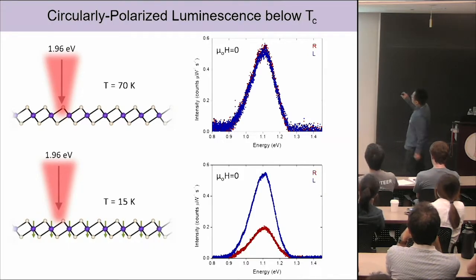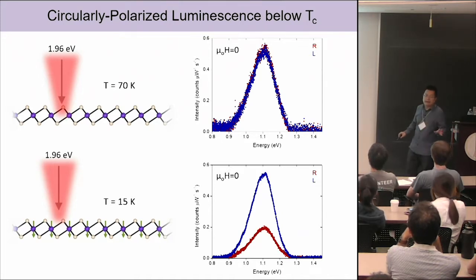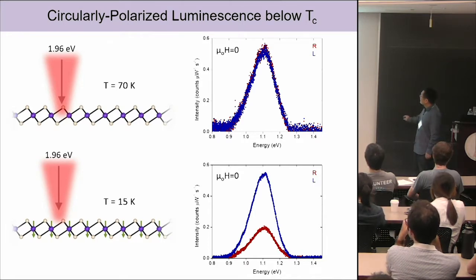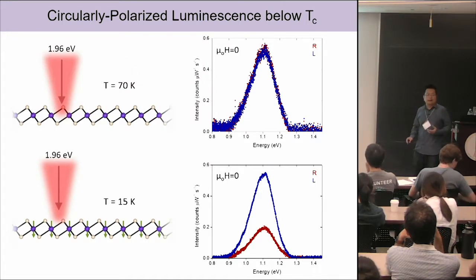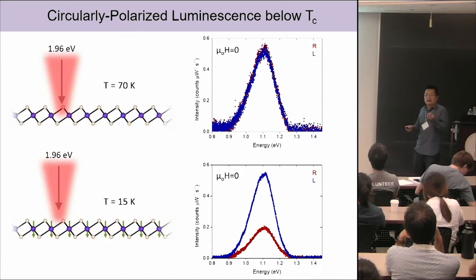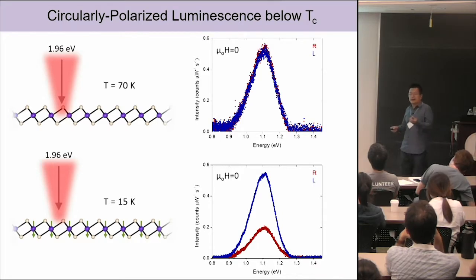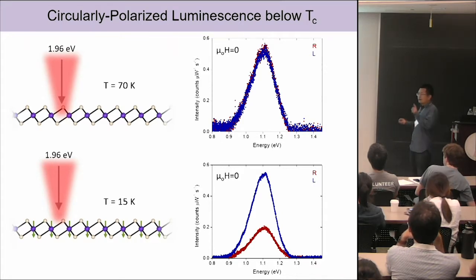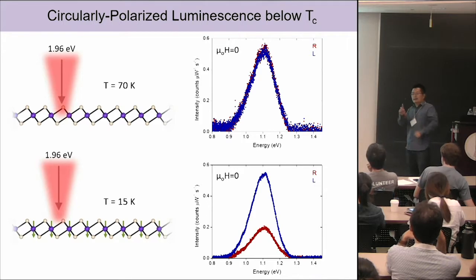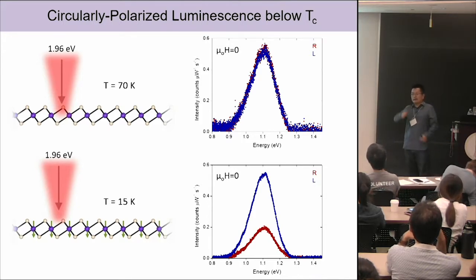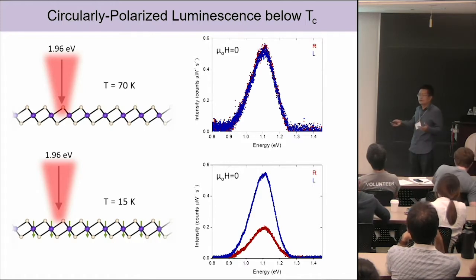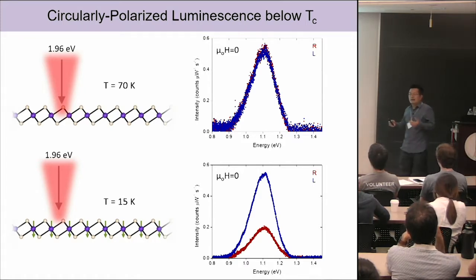Then next, we cooled down the sample to 15 Kelvin. Again, we don't apply any magnetic field. There's no magnetic field applied in the whole process. Now you see there's a spontaneous circular polarization in the system. This PL shows it's circularly polarized. This demonstrates that indeed a ferromagnetic order spontaneously formed, and it's out of plane. Out of plane is important because the light's circular polarization carries angular momentum going out of plane. If the magnetization is in plane, you're not going to see these circular polarizations. So this is an independent measurement of magnetic order.